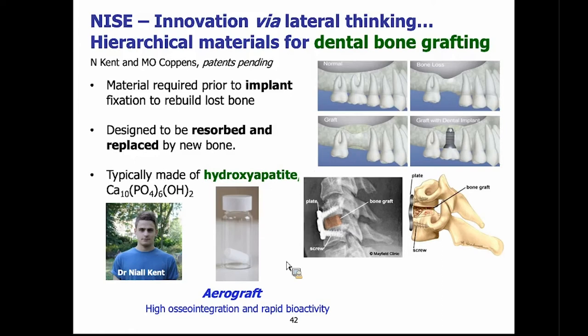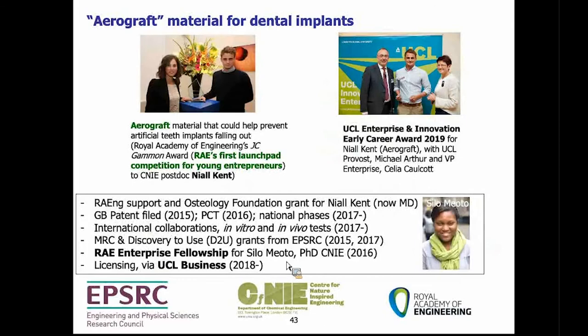inventing a material we call Aerograft, which is aerogel based and has very high osseointegration and rapid bioactivity. So what happens is that thanks to this hierarchical structure, the material can more easily integrate with the bone. You have very easy transport. You can have vasculature in it and it can grow back much more quickly than all the materials that are there.